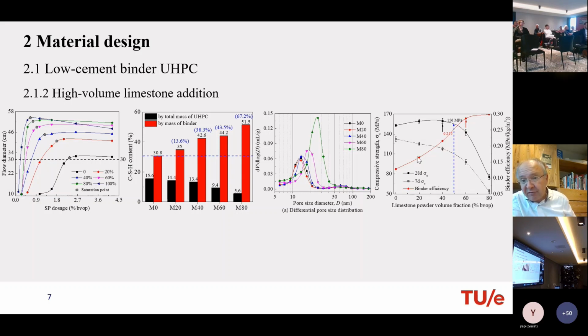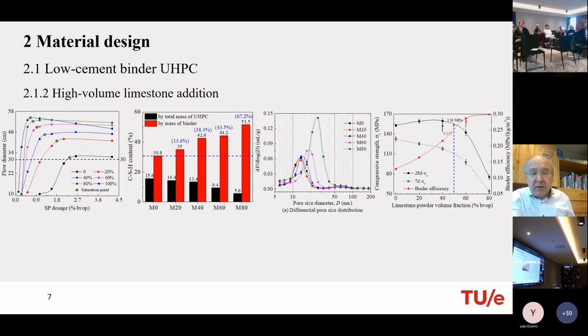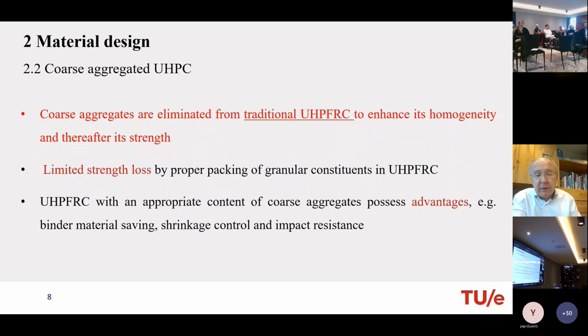Here you can see the binder efficiency. That is actually the strength that you get per kilo of cement. Well, the cement is reduced because we have more limestone powder, so there's less cement, but the strength that the cement is providing is more. But it has to do with the fact that it has the chance to react more completely, which is very interesting. And you can see then also the binder efficiency, which is megapascals per kilogram of cement per cubic meter, and that also rises when you reduce the cement and increase limestone powder. Well, that's the fine part, the binder part, where we included limestone powder in the binder.